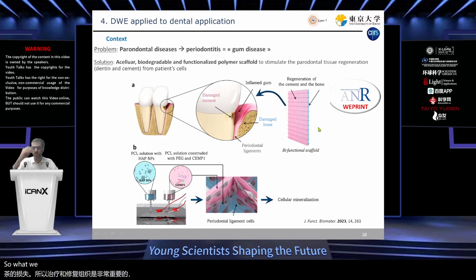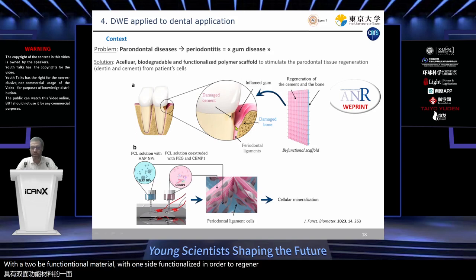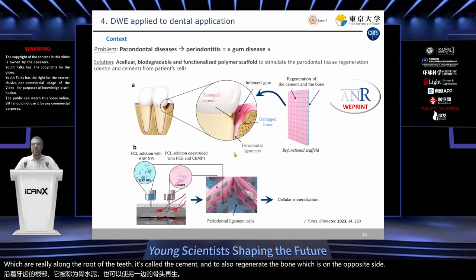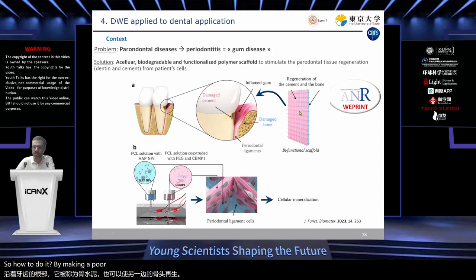So what we proposed in this project is to make a hybrid material, a bifunctional material, with one side functionalized in order to regenerate the tissues which are along the root of the teeth. It's called the cement. And the other side to regenerate the bone, which is on the opposite side. So how to do it? By making a porous material in order to allow the cells to migrate inside the scaffold, and also to allow the cells to differentiate into cementoblasts and also osteoblasts.